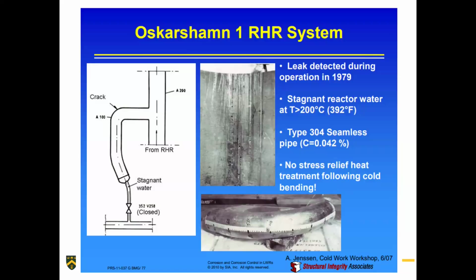In this case, this was with a particular portion of their reactor. Some of the piping, in which they bent a tube with no stress relief from heat. Bad news bears. All of that stress you've added to the metal is cold worked, with no relief from adding extra heat to the pipe. Again, it's a 304 steel with a moderate amount of carbon, so you've definitely formed martensite by doing this.